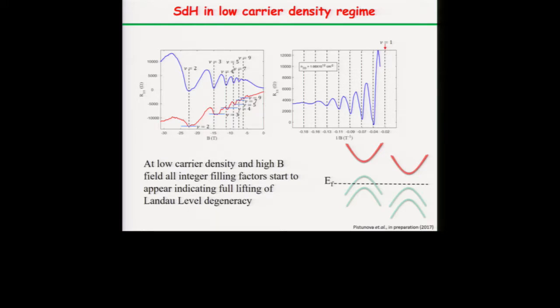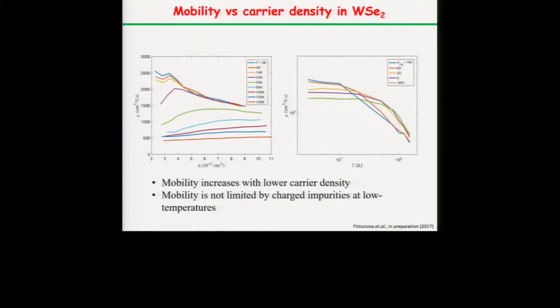In tungsten selenide, we're mostly on the valence band. So in order to have intervalley scattering, we have to flip a spin. In comparison to MoS2, in the conduction band, they are mostly degenerate, so the spin flipping is possible. So that's one of the things that is reduced, the intervalley scattering. Yeah, that could be. Right. So we are not limited by this charge impurity, like in MoS2.